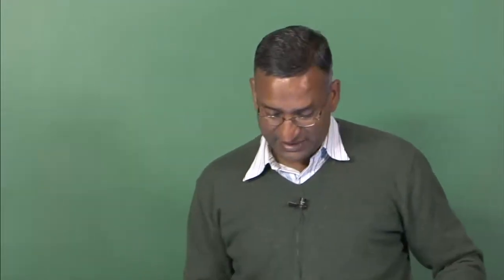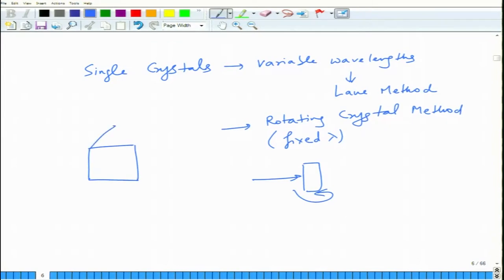See, the problem with single crystals is that if I have a single crystal specimen, and this is my incoming beam, there are only a very few planes which may be appropriately oriented with respect to the incoming beam, especially if your sample orientation is fixed. Because remember, you have to follow n lambda is equal to 2d sin theta. If your lambda is fixed, then the only two things are d and theta, which are dependent upon each other, right? So, orientation of a particular plane with a particular d spacing will not guarantee whether you will have Bragg's law satisfied or not. As a result, you need to change lambda so that a particular plane will diffract, okay?